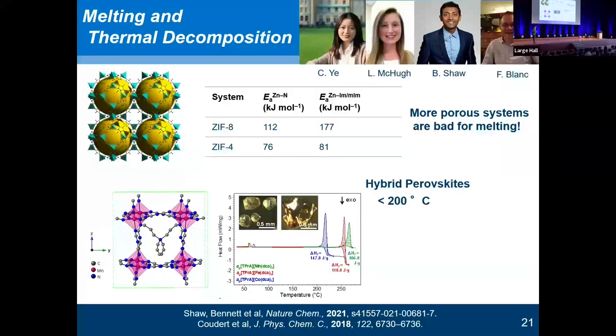ZIF-8 doesn't melt. Everybody's favorite ZIF doesn't melt. That's a huge disaster, right? Not in terms of application, but in terms of interest. Once you say ZIF-8 doesn't melt, everyone sort of turns off. Done. The reason it doesn't melt is that when you're detaching that ligand, the ligand is free in the system. It has nothing to stabilize it. No non-covalent interactions. But we can leverage that.